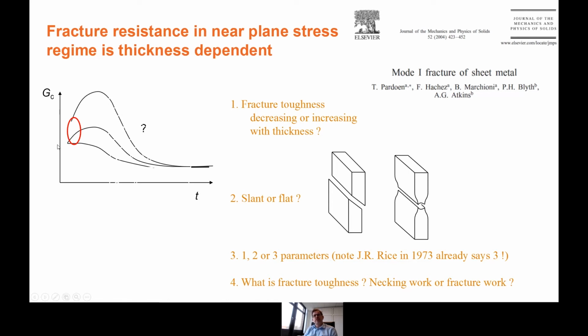Why is that? Understanding why the fracture toughness is increasing when decreasing thickness is easy. You're slowly entering the plane stress regime. The stress triaxiality at the crack tip becomes lower and lower, so the local fracture strain at the crack tip can be bigger and bigger because the damage mechanisms are slowed down. But why do you then get a decrease, and often a linear evolution, at a very small thickness? This has to do with the work of necking, and I will explain that in a second. Other questions to understand this effect of thickness are related to the slant mode versus flat mode. So do you have a mode 1, mode 3, or do you have a flat fracture?